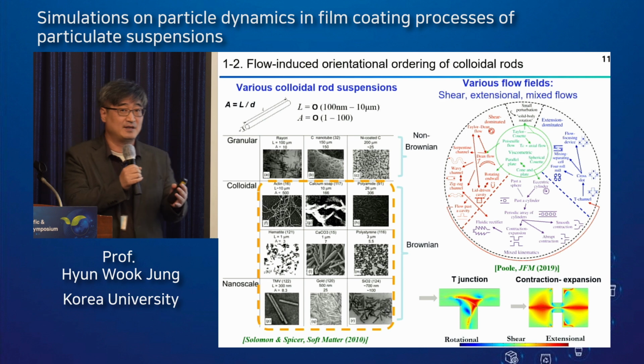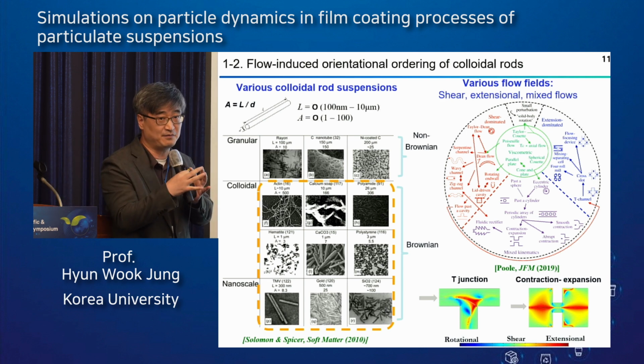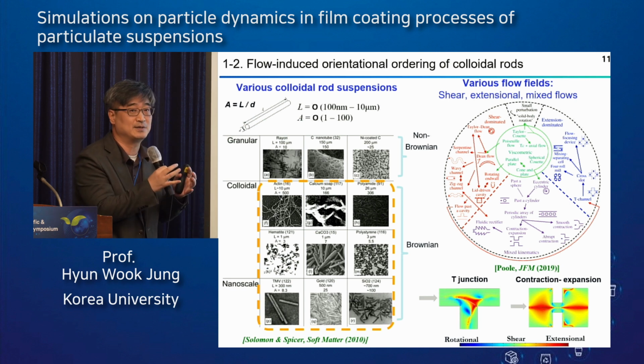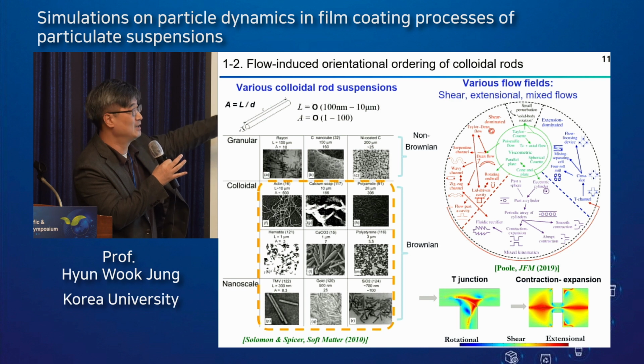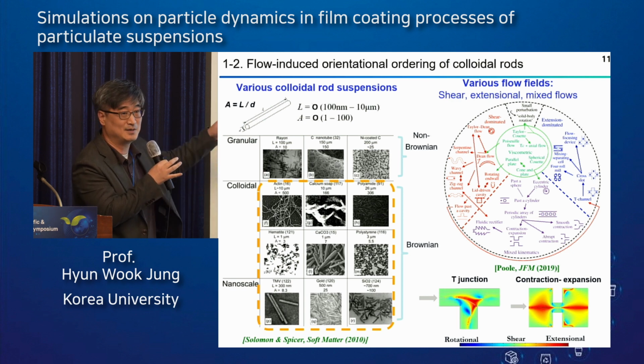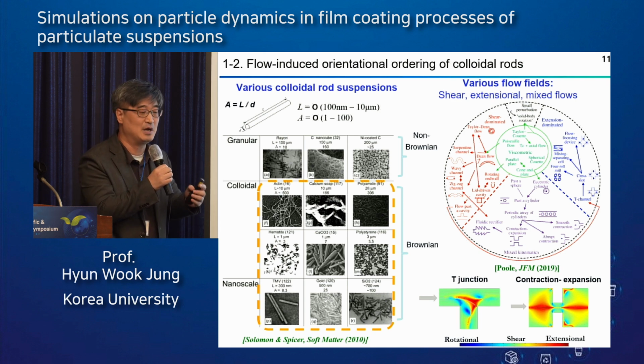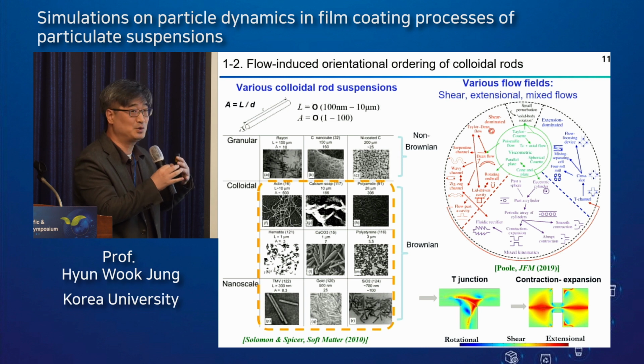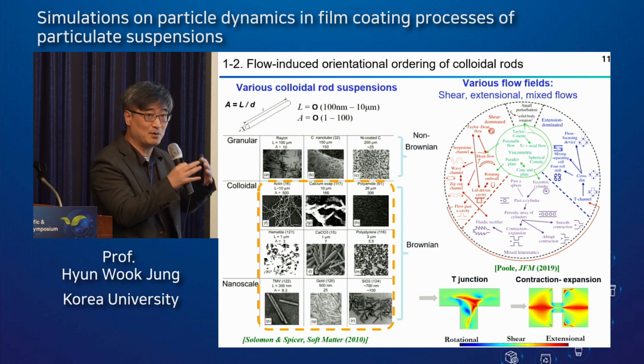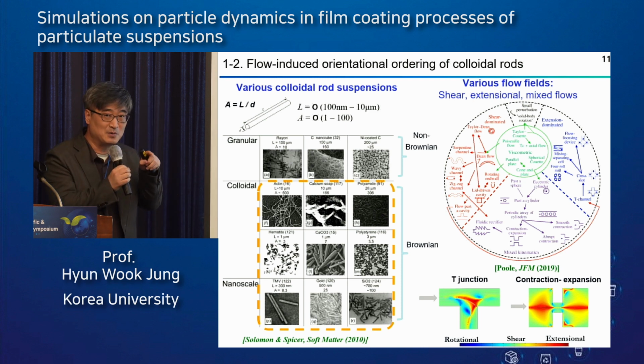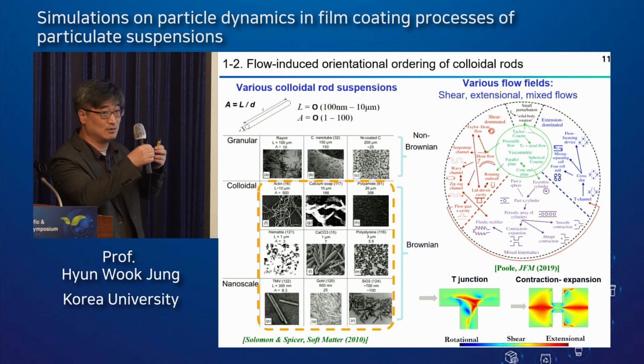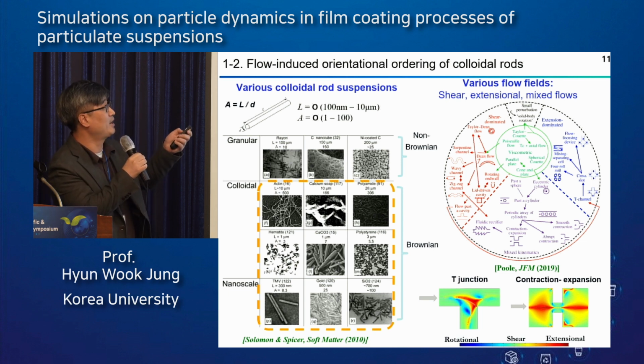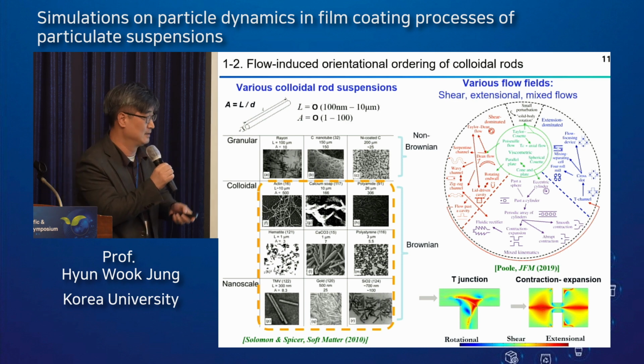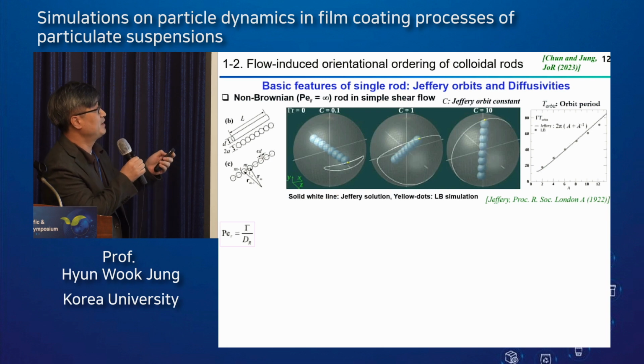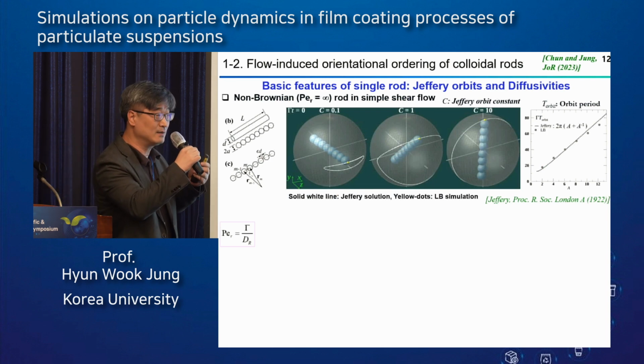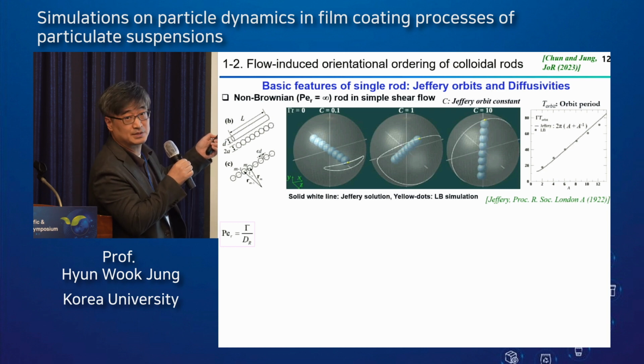So we have further extended to non-spherical particle systems and various flow fields, because many coating applications consider many kinds of particles, covering the non-Brownian case and Brownian case here. Also, these particles will experience very complicated flow fields, like shear-dominant flow, extensional-dominant flow, mixed flow, and so on. So up to now, we have only focused on the motion of rigid colloidal rod particles and their orientation ordering depending on the flow field. We successfully designed the rigid colloidal rod as a non-overlapping chain of spheres, as shown here.